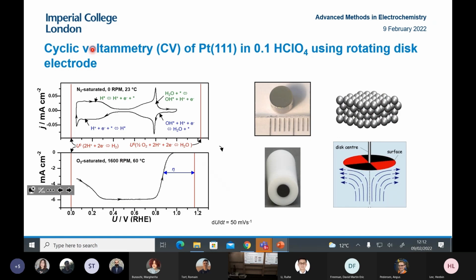So the simplest system you can look at in terms of experiments, and the easiest one to relate to theoretical calculations, is platinum 111. It's a closely packed surface of platinum. Like I said, you have a disc that's 5 millimeters across. You put it into a shaft that rotates. It's called a rotating disc electrode. And then you do electrochemistry on it. So, this is a cyclic voltammogram in perchloric acid.